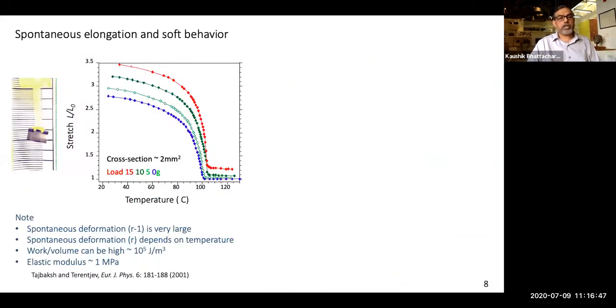And the result of this is that as you change temperature in these materials, you find that there is a very large change of shape, as you can see in this movie, hopefully. And again, this is kind of the measurement of this. This is temperature versus the stretch. And you can see the stretches are huge, factors of 2 and 3. The modulus of these materials are of the order of 1 megapascal, maybe 100 kilopascal. So the work that this small piece of rubber is capable of doing is actually extremely large. It's 10 to the 5 joules per meter cube. And that's comparable to the best actuator materials, and in fact is comparable to what you get from hydraulic machinery. So though this is a soft material, this can be a very powerful actuator.